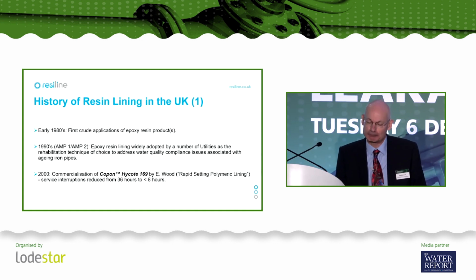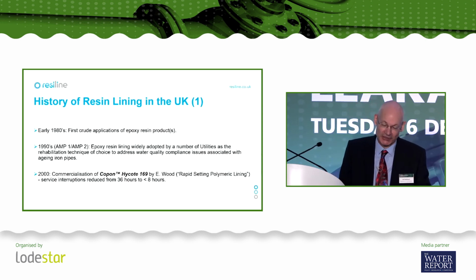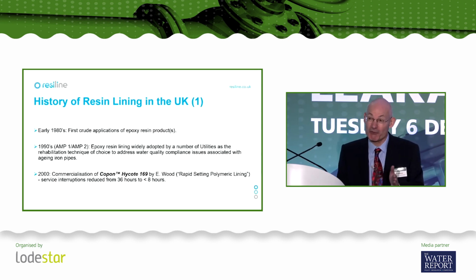36 hours. So this was to allow for cleaning of the main and application of the epoxy resin, but then there was a minimum 16-hour period during which absolutely nothing happened. So the epoxy resin had to be left overnight to actually harden, and then the following day you could set about disinfecting, flushing the main, and return to service. So there was a period of 36 hours when nobody had any water.